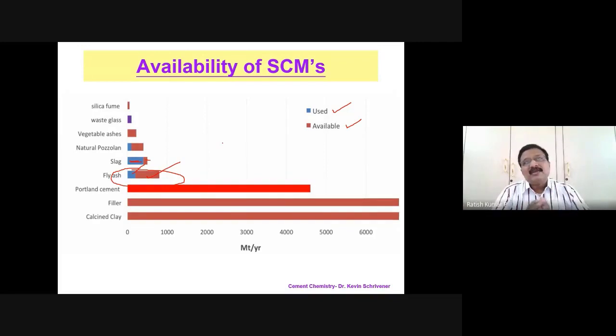So that is the reason why I don't want to really talk about the success story or the failure story of geopolymer concrete, but definitely a good amount of slag should go into the formation of geopolymer concretes. But as you can notice here, the amount of slag available has become less, because it can actually produce a good type of material. But the point is that it's coming to be less. So that's why today we are trying to combine slag and fly ash, or people are even trying to use fly ash plus other forms like rice husk ash, which is nothing but the vegetable ash here. Or people are trying to use a combination with waste glass as well as metakaolin also, which is something like the clay type.